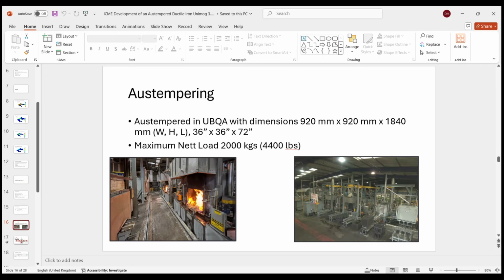When, for example, we look at this lift arm for Atkinson Vos, in our furnace we can heat 12 castings at 55 kilos each. So that's only about 700 kilograms of castings in the furnace load, where we can heat treat up to 2 tons. But we have to look at how we load the castings and the size of the castings to optimize the loading, to minimize any movement of the casting in heat treatment, but also to ensure that we get the best throughput and therefore offer the customer the lowest unit price.